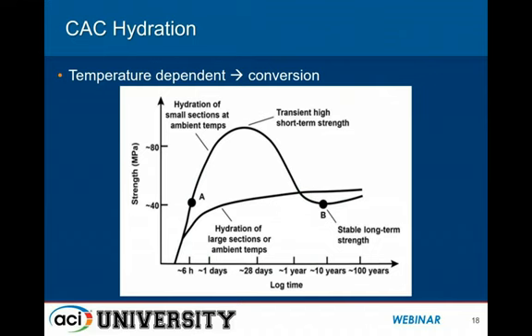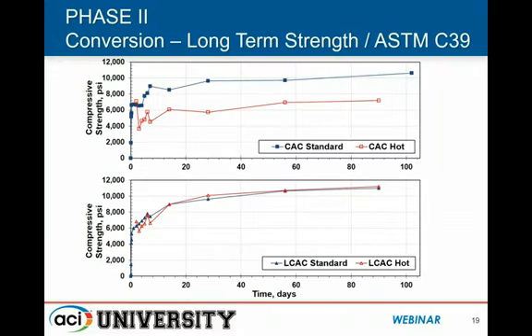But when we're talking about concrete repair, we set out to investigate this material, understanding that strength really wasn't our concern. What was ultimately done here was we investigated these two different types of temperature histories for how they affected durability. And I think that's really the critical thing here, that the durability properties were studied closely, and we wanted to ensure that it wasn't just strength that we were after for that early opening time.